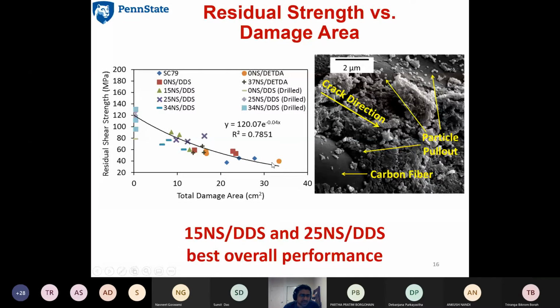And what we found was that the two concentrations that worked the best for our systems were 25 and 15 weight% of nanosilica in this particular type of curing agent called DDS. It was really good because DDS is the type of material that is used in thermosets also. It gives a really high Tg, or glass transition temperature. That's the temperature where a material transitions from glassy to a rubbery state. So this turned out to be really good, that the DDS resin showed the best performance.